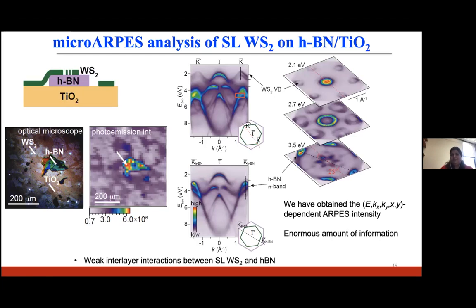Here we use micro-ARPES, where the spot size was about 10 to 12 microns. In this study, we did all our measurements at the spot I'm showing here by this white arrow. Here's the dispersion of the single layer WS2 along the K-gamma-K direction. We have very sharp bands, and we can clearly see the splitting in the valence band. Here I'm showing the dispersion of the hBN along the K'-gamma-K direction.